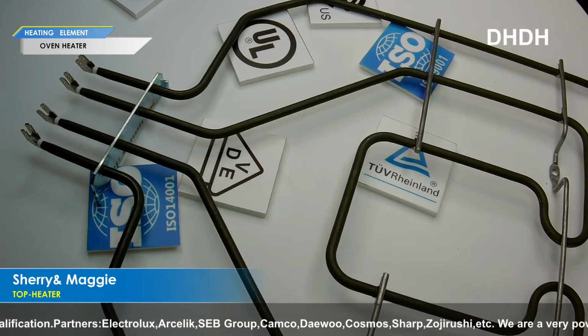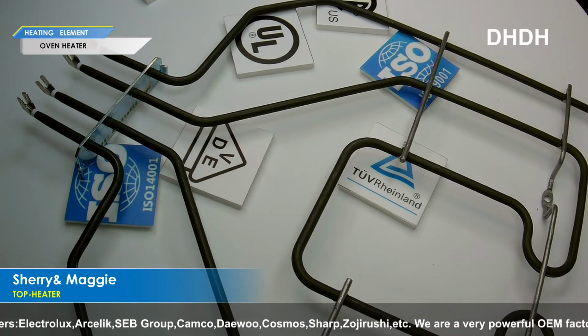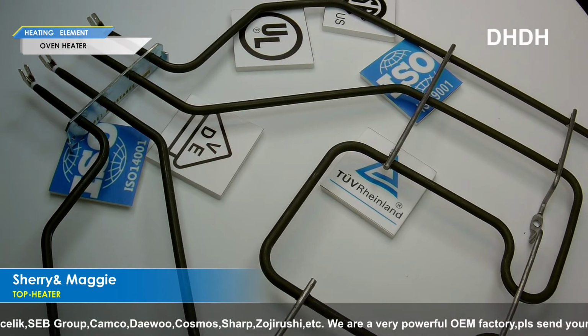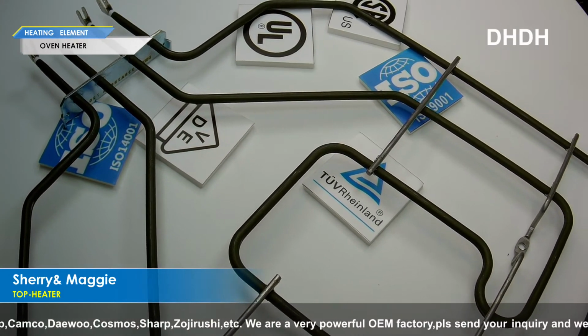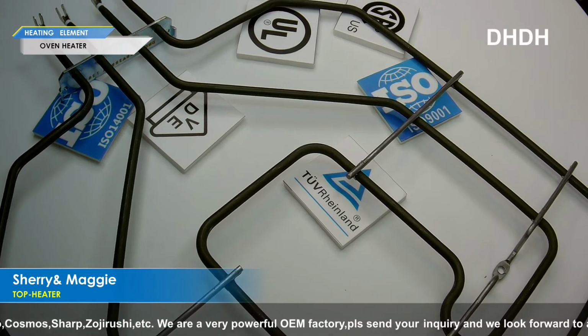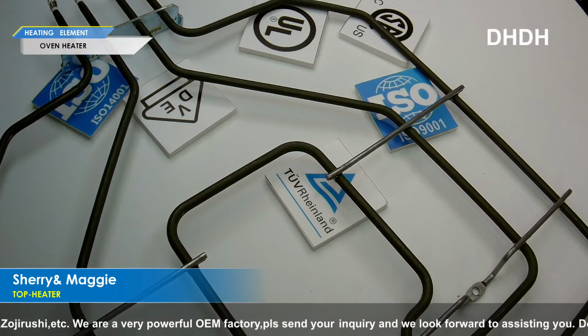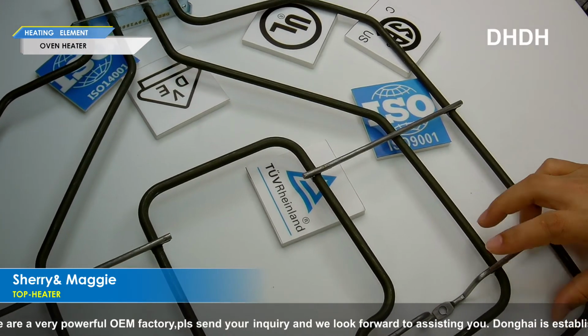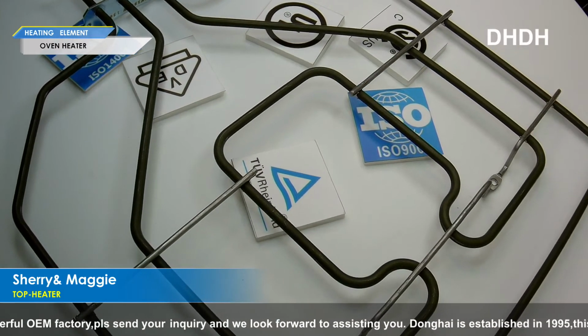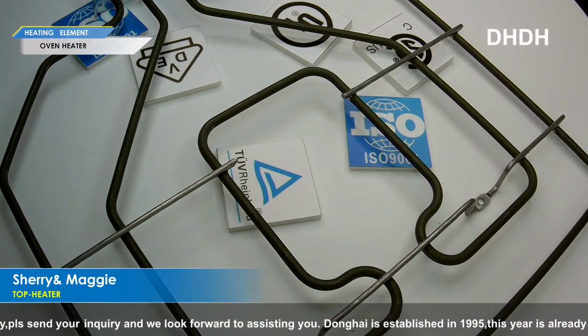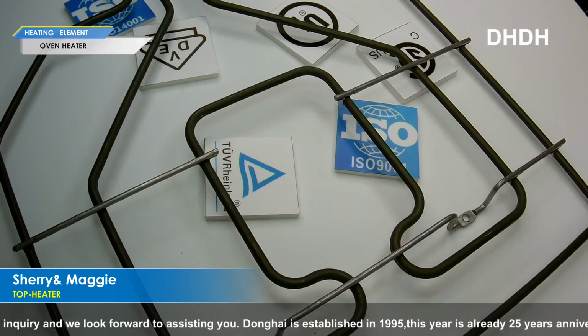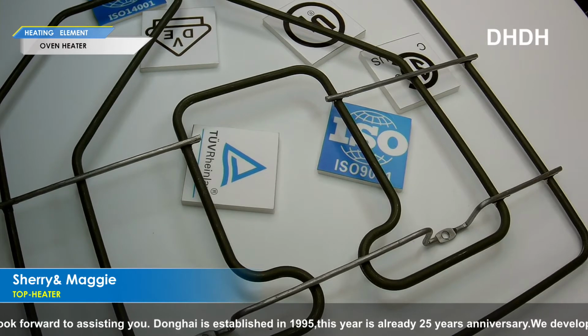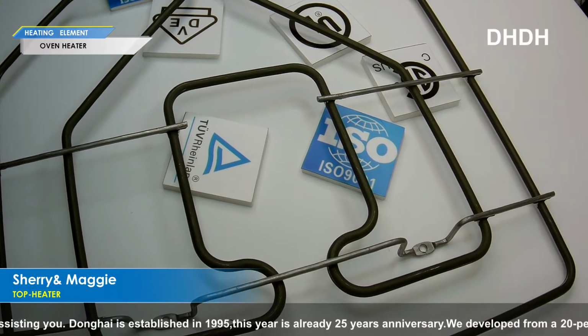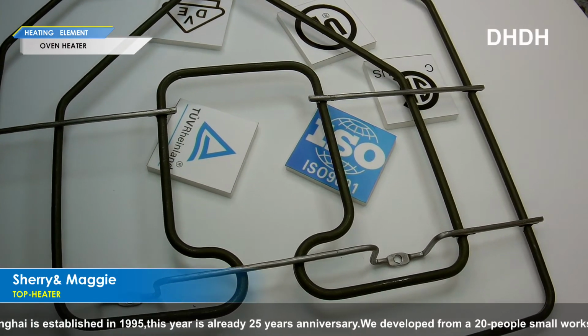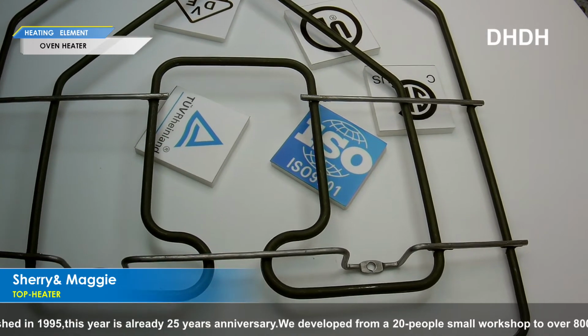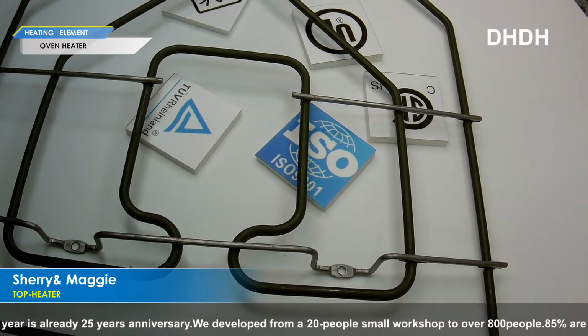And in order to save cost, some suppliers will use lower grade MgO, and it's dangerous because lower grade MgO needs to be filled with silicon oil. And the oven is working at high temperature. In such a situation, the silicon oil will run during the high temperature.